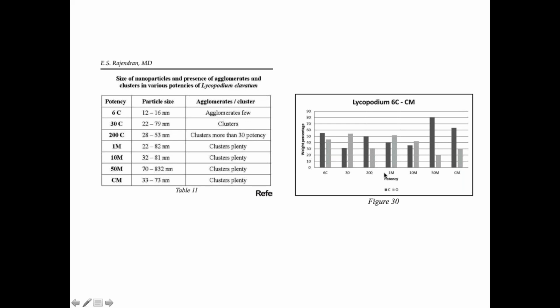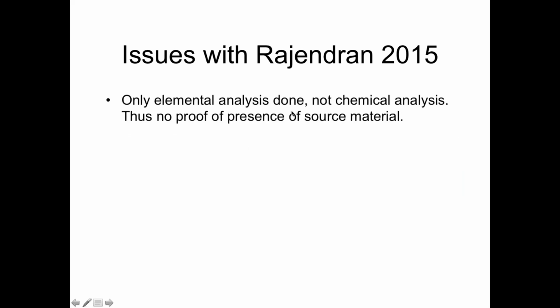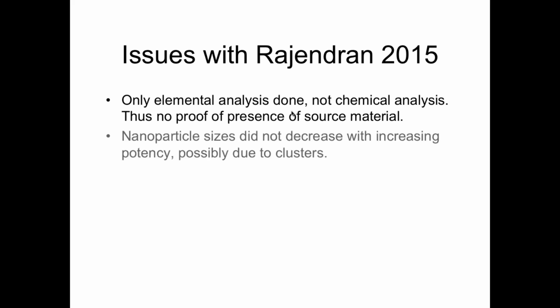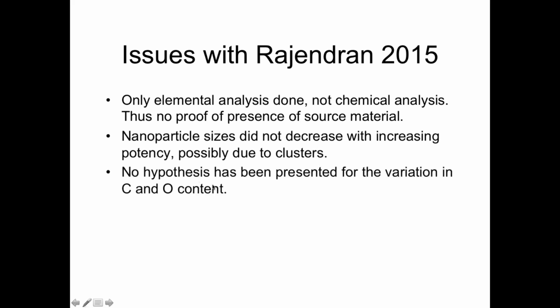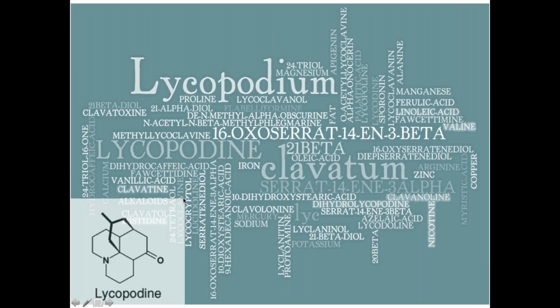So the problem with this study is that because they didn't do a chemical analysis, you can't prove that the starting material is there. But with a plant product, this is very difficult. Why? Because we know Lycopodium clavatum has dozens and dozens of ingredients in it. So which chemicals are you finding? And it might vary from potency to potency. Nanoparticle sizes did not decrease, probably because of the clusters. He didn't present a hypothesis why there was a variation in carbon and oxygen content.